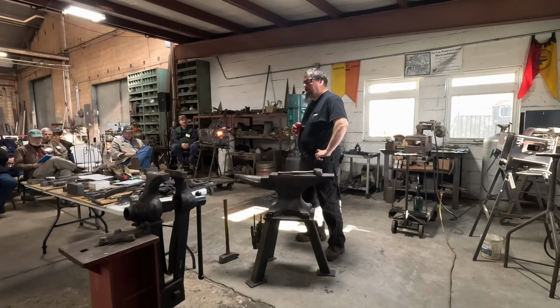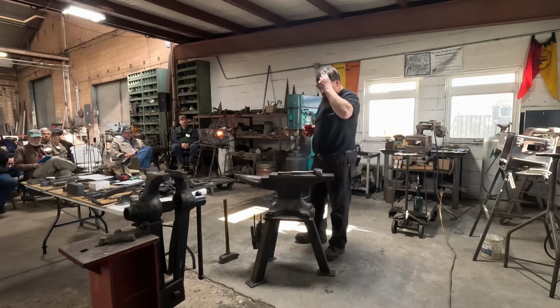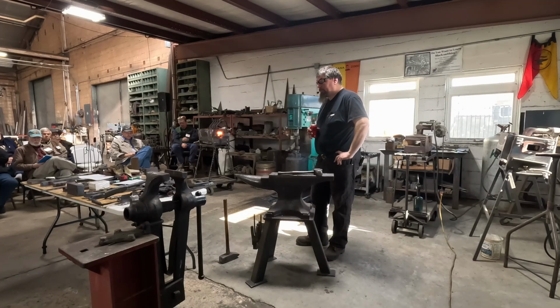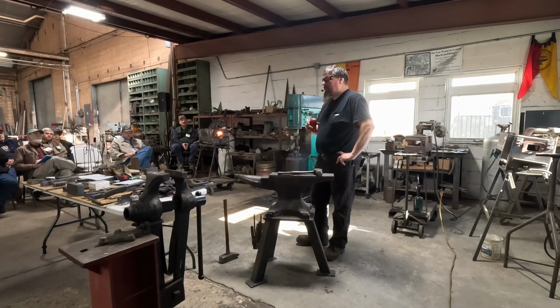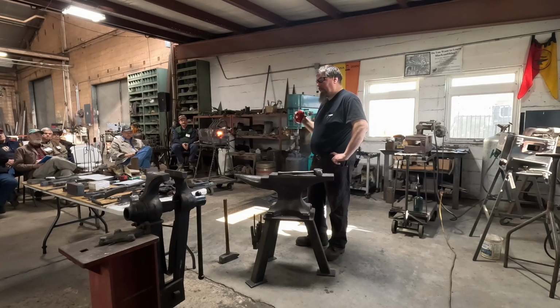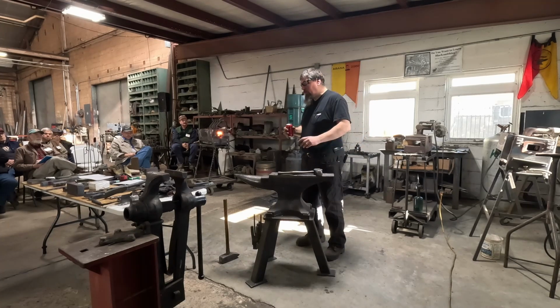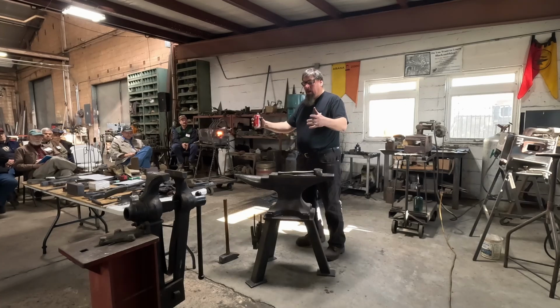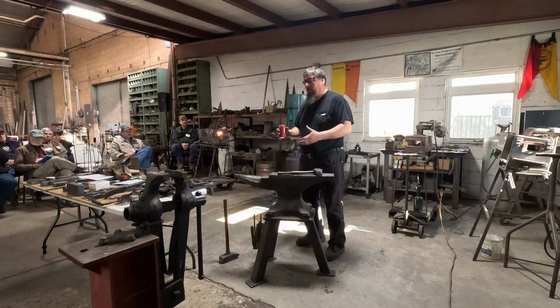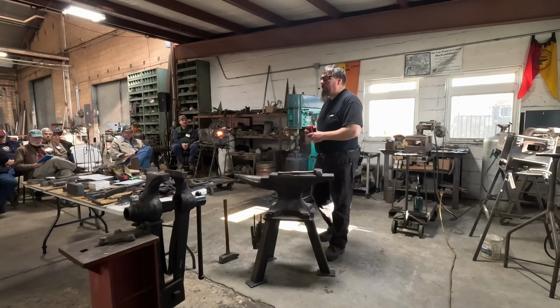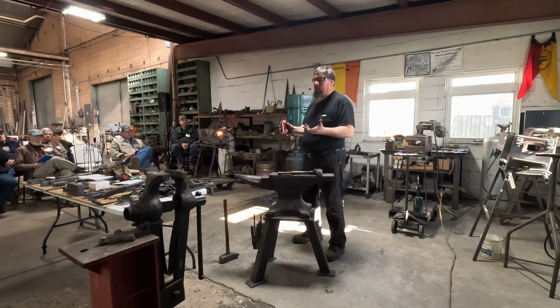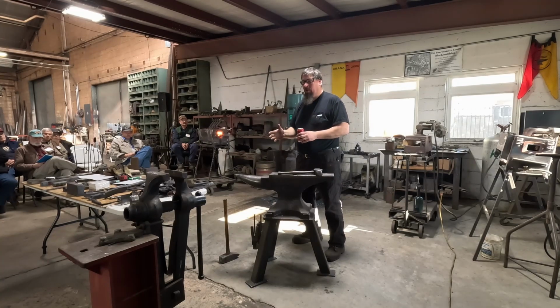But he also talked about the need to cool things fast enough. If you don't cool them fast enough, they won't get hard. So how fast is fast enough? Well, you could actually put numbers on that, which I don't recall, but it is actually really fast. But fast enough varies an awful lot with the type of material you have and the size of the workpiece. So to simply answer the question, which was, how much volume do I need in my average everyday blacksmith shop environment to effectively heat treat things that I might make, I would recommend at least 1 gallon per pound of whatever it is you're doing.